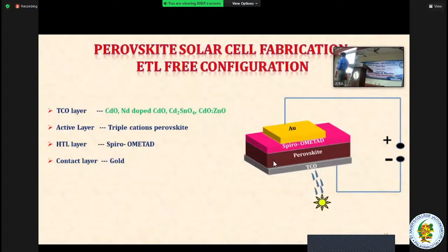These materials we prefer as the TCO layer, and then the active layer, which is the conventional material, a triple cation perovskite. Then the HTL layer was spiro-OMeTAD, an organic material used to make the HTL layer, and the contact layer was gold. So this is the architecture of the ETL-free perovskite.